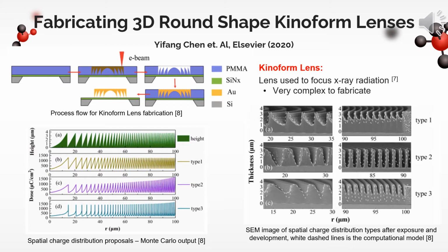After exposure, the resists were developed using IPA:H2O in a 7:3 ratio for 4 minutes. Then, gold was electroplated into the resist profile, making the lens. This process flow is shown in the image on the top. Taking advantage of the high degree of control and precision involved with GEBL, this group was able to create a kinoform lens capable of focusing X-rays into nanoscale spots with object magnification.